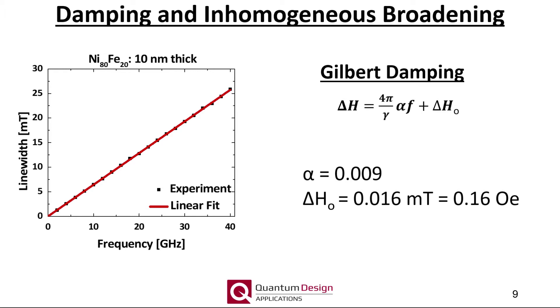The frequency dependence of the line width for the same sample is shown here, along with a linear fit. The slope is directly proportional to the damping parameter alpha, and the y-intercept corresponds to the inhomogeneous broadening. This analysis clearly shows the importance of a broadband measurement, as a fixed frequency measurement would not allow one to determine the slope nor y-intercept. The inhomogeneous broadening is generally used as a relative indicator of the lateral homogeneity of the measured film, where a smaller value is generally better. Note, the NanOsc software assumes a simple linear Gilbert damping contribution. There are other damping mechanisms that can be present, for example 2-magnon scattering, that are not linear and may require more advanced post-processing.